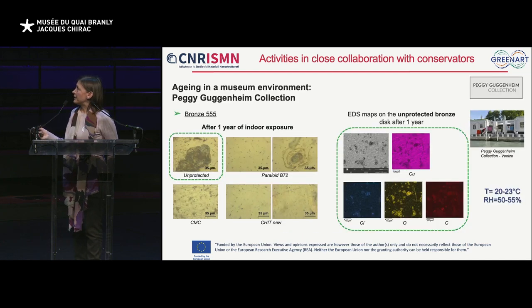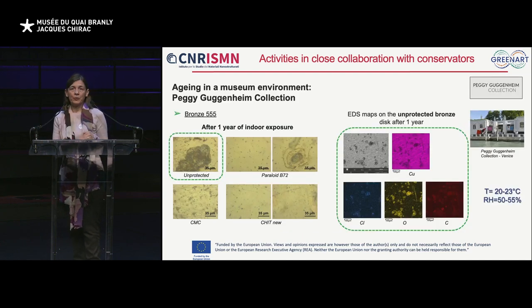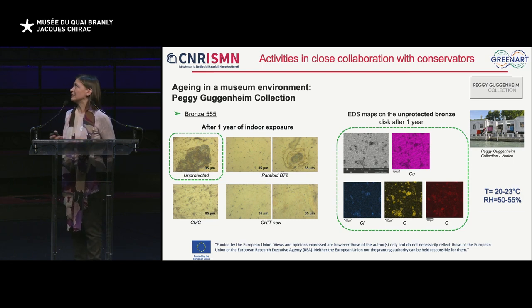And after 1 year of treatment, we can say natural aging in a real museum environment, we observe by optical microscopy the presence of alteration products on the surface of the unprotected mock-up, but also the presence of some alteration spots on the substrate coated with the commercial product. The best performing was the formulation based on chitosan.